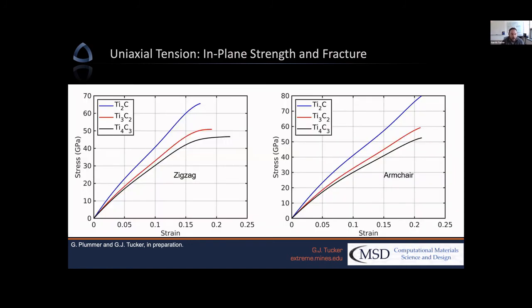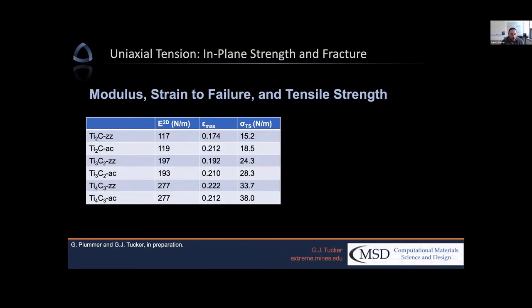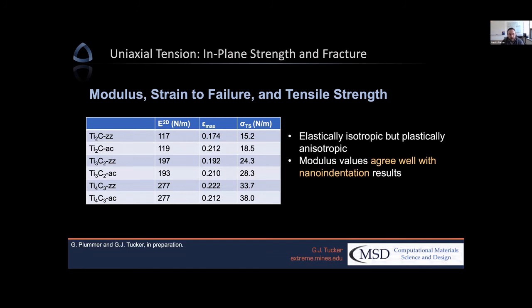And so when we do that, here's the stress strain data for those studies. We have all 3 of our titanium carbide MXene systems plotted here. And then we did it at 2 different in-plane orientations, both the zigzag and the armchair orientations. And you can see there is a dependence, obviously on the stoichiometry, but also on the orientation at which we pull in plane in the MXene itself, both on the strength of it and the strain at which fracture occurs too. And these data are very important, but really we want to understand some of those fundamental mechanisms which lead to fracture. And so here is actually a comparison of the modulus, the strain to failure, and the tensile strength from those plots, comparing the different MXene systems and the different orientations.